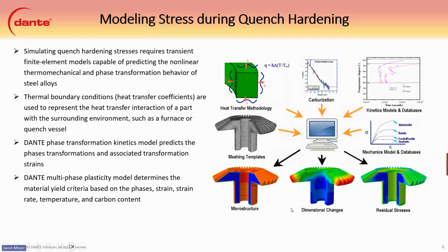You can see on the contours here below, you can see the different phases in the microstructure of the part. So different martensites or different phases of the material. We get dimensional changes, so we can predict the distortion that occurs. And then more importantly for quench hardening, quench cracking, here are the residual stresses that occur during the process or even after the process.